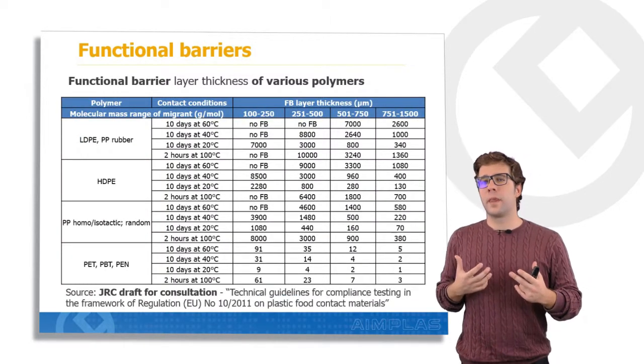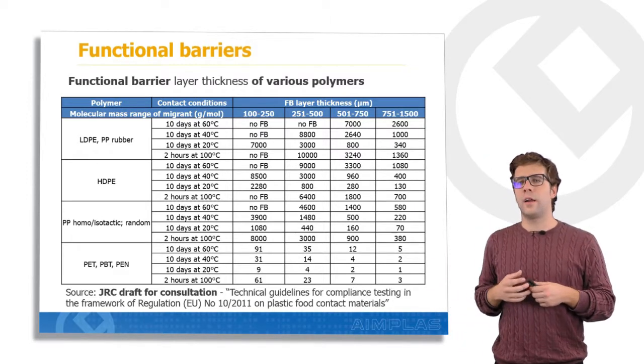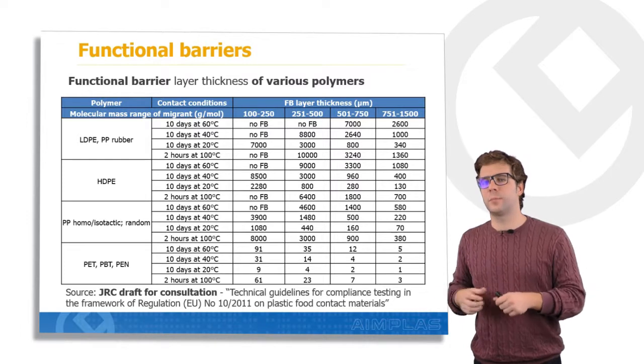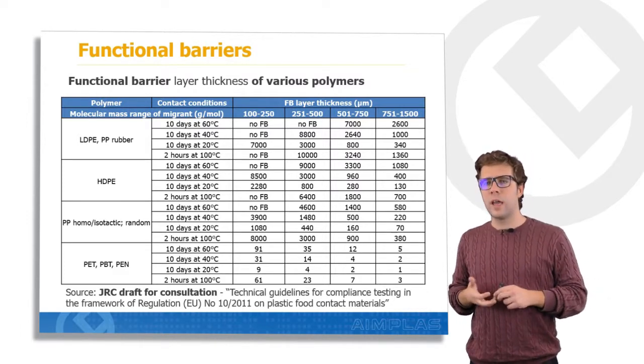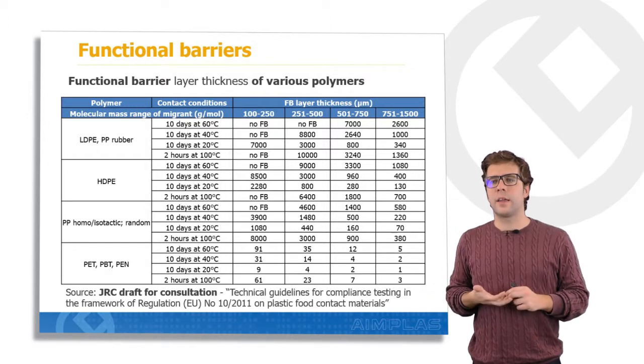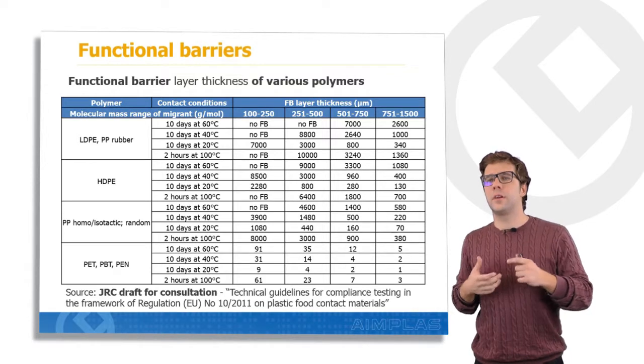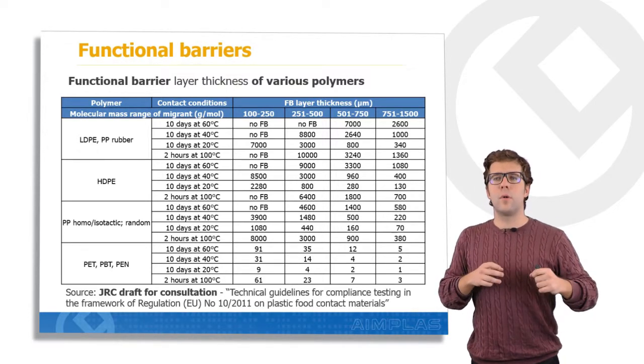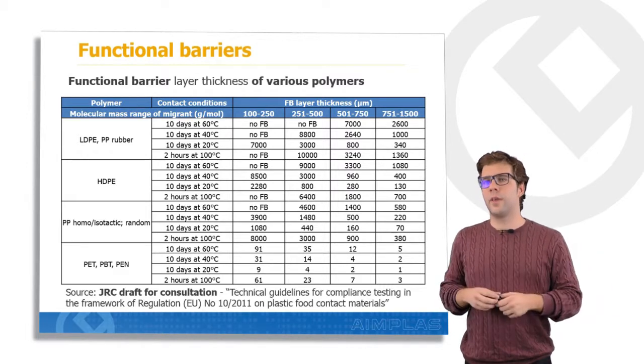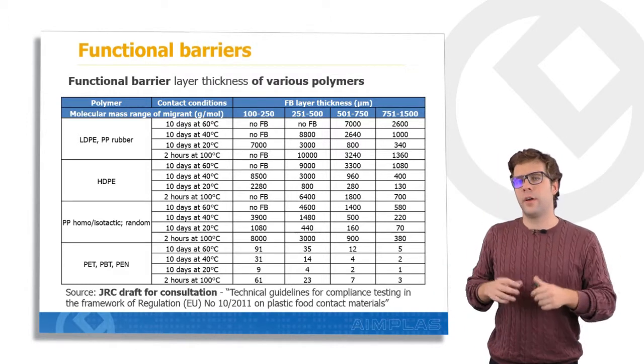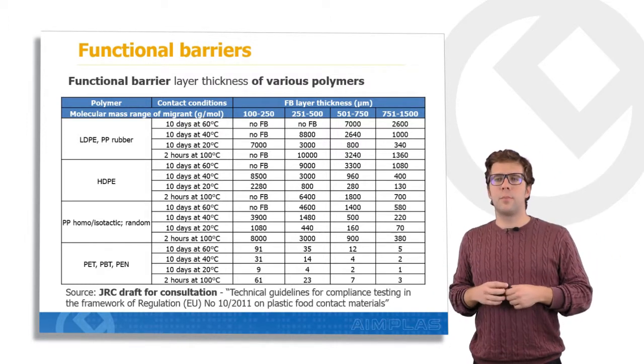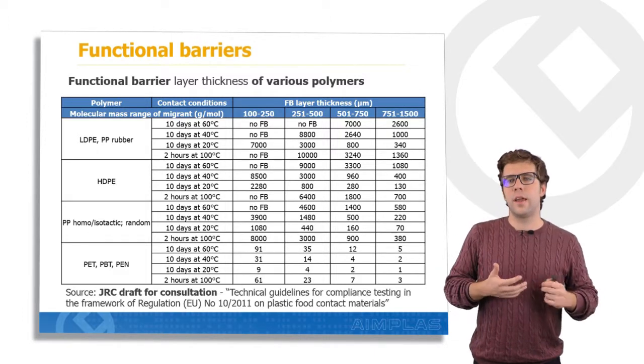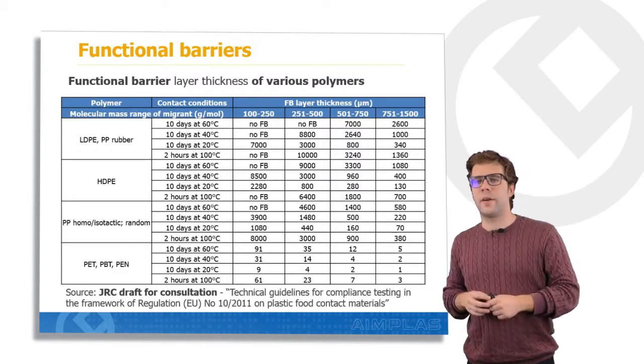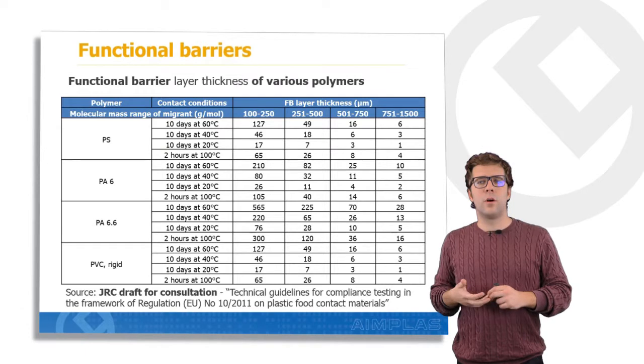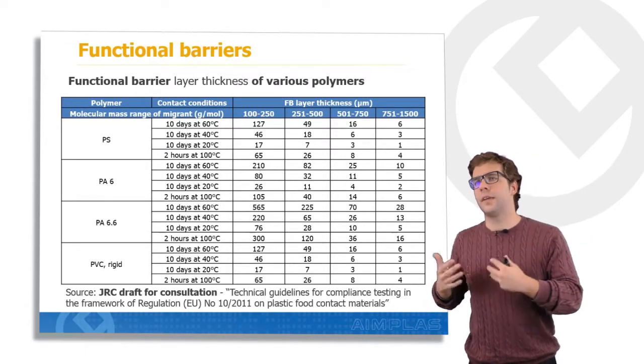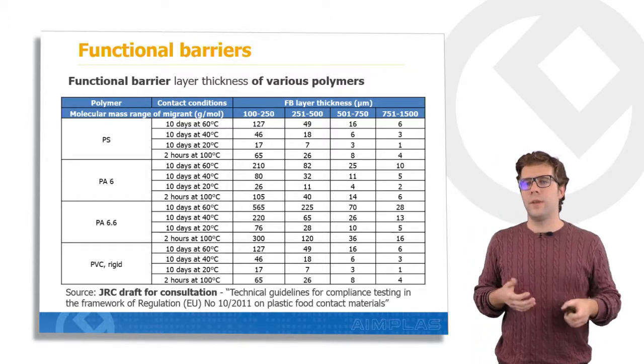Here we have some examples of functional barriers. These are results from a study on functional barriers performed by the Joint Research Centre of the European Commission. We have different polymers that can act as functional barriers under different contact conditions and with different molecular mass ranges of migrant of the recycled layer. We have examples for low density polyethylene, for polypropylene, for high density polyethylene acting as functional barrier, also for PET, and also for other materials typically used for food packaging applications like polystyrene or even polyamides.